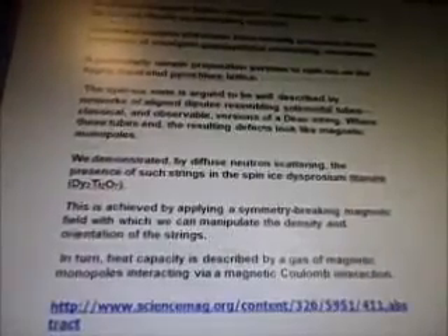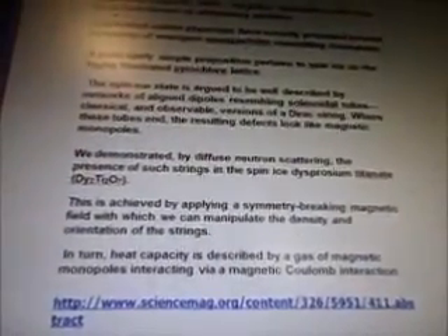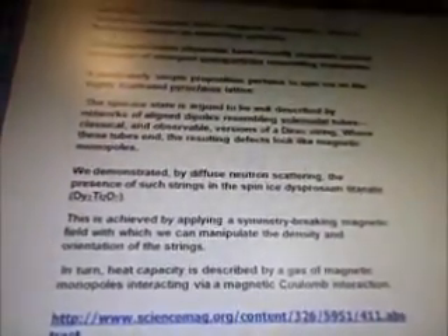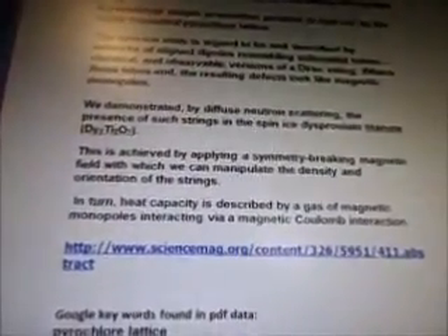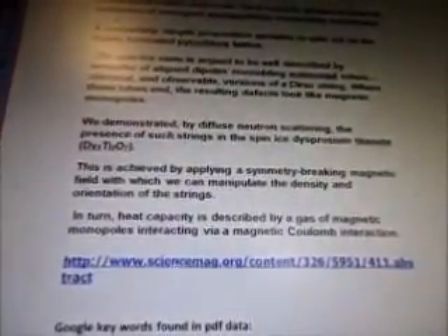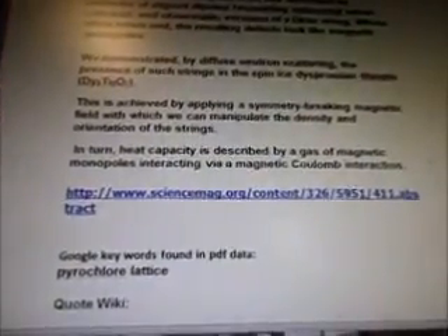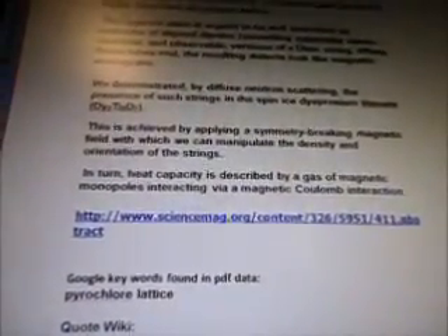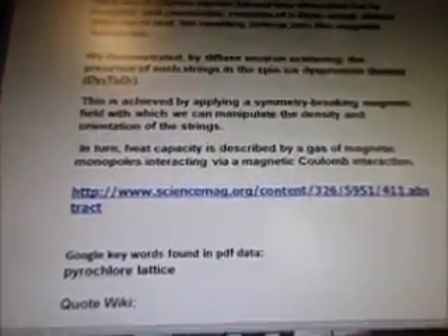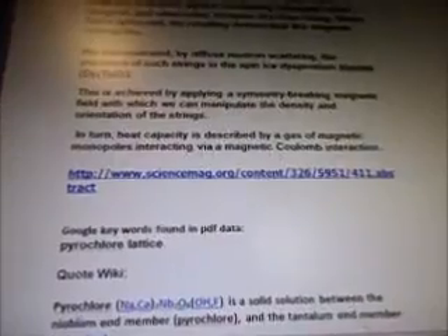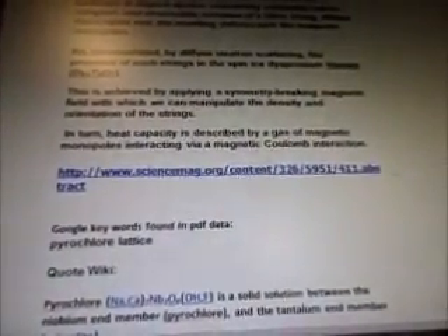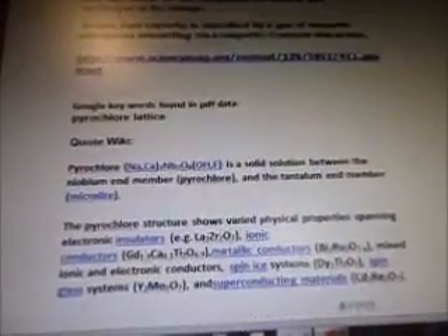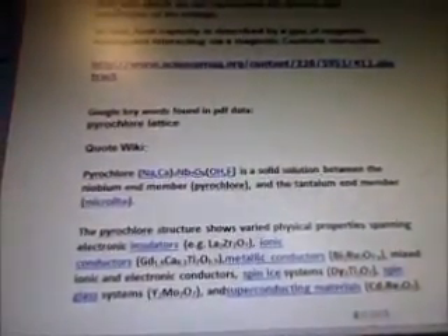The spin ice state is argued to be well described by networks of aligned dipoles resembling solenoidal tubes, classical and observable versions of a Dirac string. Where these tubes end, the resulting defects look like magnetic monopoles. We demonstrated by diffuse neutron scattering the presence of such strings in the spin ice dysprosium titanate, Dy2Ti2O7. This is achieved by applying a symmetry-breaking magnetic field with which we can manipulate the density and orientation of the strings. In turn, heat capacity is described by a gas of magnetic monopoles interacting via magnetic Coulomb interaction. That's from sciencemag.org. So I'm going to Google the keywords found in the PDF data, pyrochlore lattice.